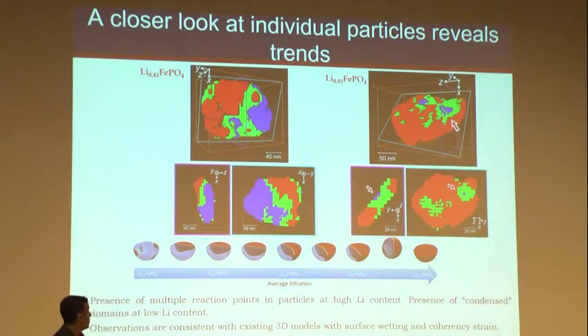Both of these particles were in the same sample. Again, this was a partially dilithiated sample. We knew the average state, but each particle does whatever it wants to do. You can see when it's at very low levels of dilithiation, there's kind of like spots where the reaction is happening, like what I had shown before. When you have a much greater extent of dilithiation, there seems to be a trend for particles to have more condensed domains. There would be 2 domains in one particle.